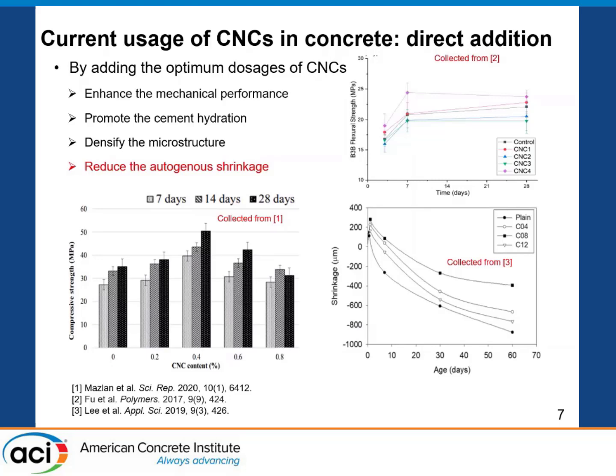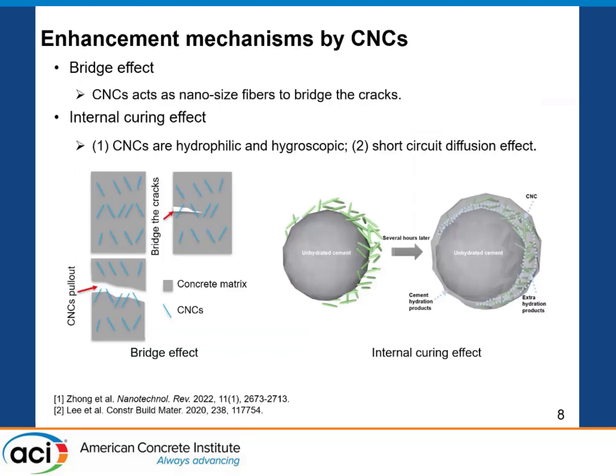And also it can reduce the autogenous shrinkage when people use it in the concrete system. Based on the literature, there are two effects for the enhancement. One is that CNCs, as I mentioned, have high Young's modulus and high tensile strength. It is very good, and it's nano sized. It provides a very good bridge effect, bridging the nano scale and micro scale cracks. This way, it can improve some of the flexural properties and compressive strengths.